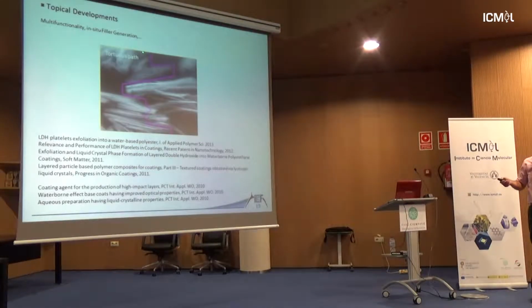On top of that, you have tortuous paths, because you have anisotropic objects. So if you want to cover some packaging, for instance, an application for polymer, you want to avoid gas permeation, like oxygen or water, going into what you try to protect from the outside. You have all this barrier effect, so that's of interest. And knowing that you can tune the composition, the intra-composition, you can also tune what is inside, so you can release what is inside the LDH, so you can have an active or self-healing component.